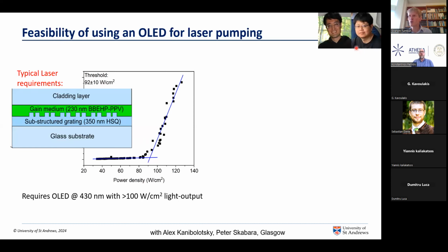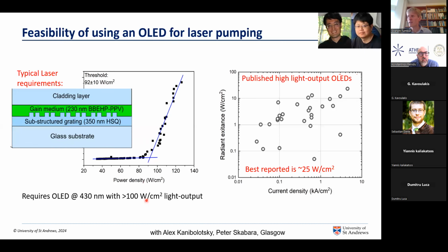Just to show the scale of what we need to do, here's our typical everyday organic semiconductor laser using this substructure grating. We need OLED outputs of 100 watts per square centimeter to drive this laser above threshold. However, the field of pulsed organic LEDs wasn't in the right place. The best anybody had achieved before we started this project was about 25 watts peak power density per square centimeter, which was somewhat too low to drive a laser.